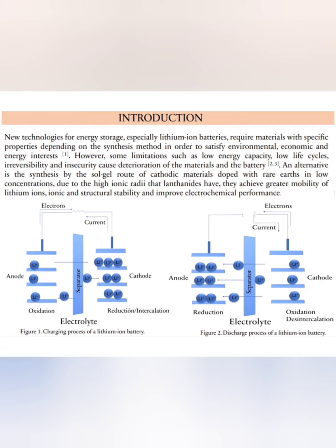An alternative is to dope the structure of the cathode materials with a rare earth ion to improve the electrochemical response of the battery. Doping with terbium at low mole percent concentration will allow greater use of the properties of the cathode materials. When doping the structure, it will cause a local distortion in the substitution site, with a partial decrease of cobalt, because the radius of the rare earth is greater than that of cobalt. Structural, chemical, and thermal stability are increased, and the volume of the cells grows for greater transport of lithium ions, which will favor the energy capacity of the battery.